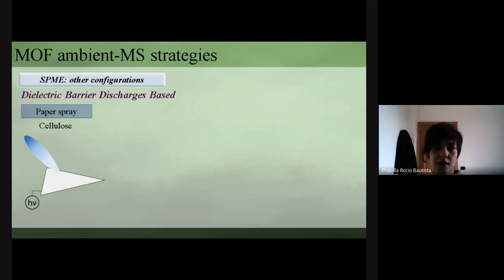The last research line to discuss in this seminar is coated cellulose, to use it as conventional paper spray. The previous strategies we have been talking about consist of the immersion of the device in the sample. But what about the deposition of the sample droplet on the device? If we are able to control the growth of MOF in a small area of the paper, a few microliters of sample can be deposited on it without losses coming from paper impregnation. The target compounds are retained on the MOF surface area.